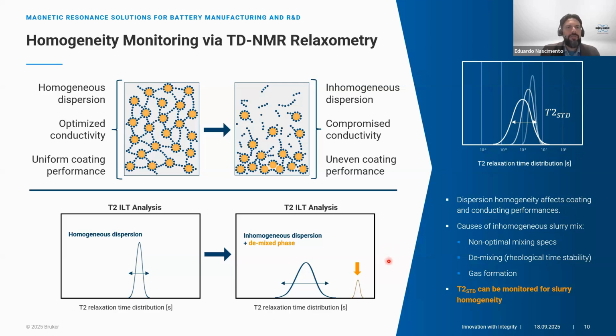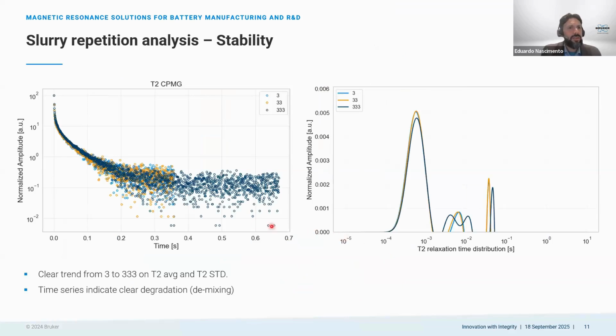still valid. And we even had some great case here where we were analyzing anodes with silicon doped, and you can also see gas formation, indicating that the mixing and the gas formation were occurring at the same time. So you see here a quick example of a slurry sample that we received. We analyzed that at 3 different times: in the morning, afternoon, and another one at the end of the day.